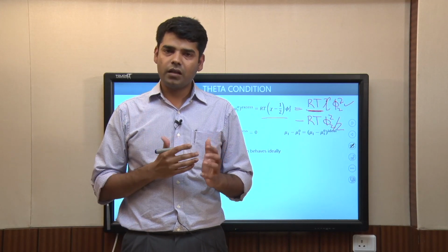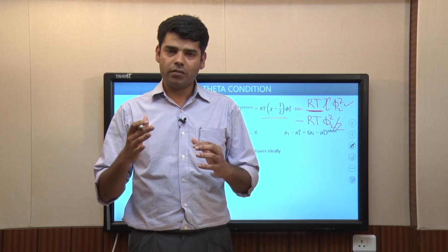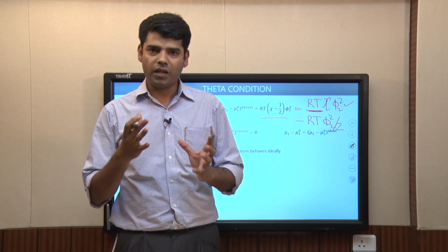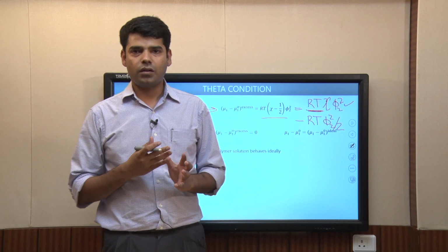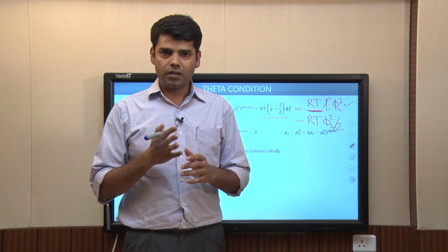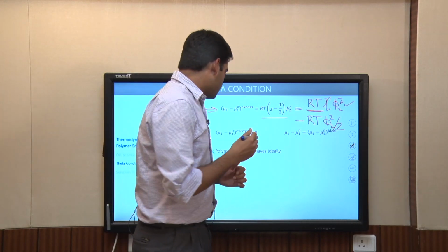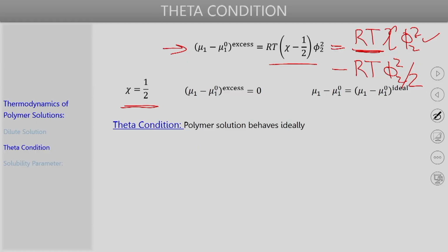There we also discussed the special case where the excluded volume repulsions of the polymer segments get balanced by the solvent segment repulsions, so that the polymer chains adopt their ideal sizes or unperturbed dimensions. That was a discussion of the theta condition from the point of view of polymer chain dimensions and interactions, and here the same concept of the theta solution is being discussed from the point of view of polymer thermodynamics.